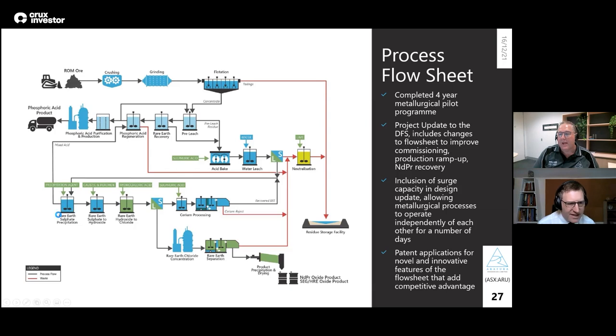So once we've precipitated out the rare earth sulfate, we separate the solids and the liquids. And this mixed acid, which is the liquor phase, now contains about 10% phosphoric acid from the phosphates leftover in the material.